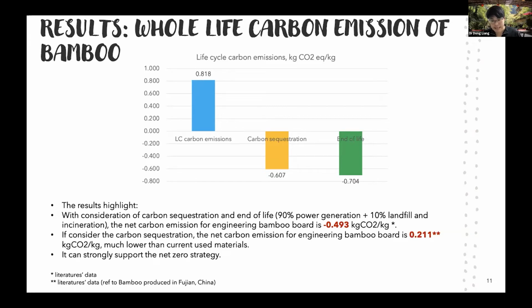For example, I applied the scenario from the European Union. 90% of the bamboo waste goes to power generation and only 10% will be landfilled. The benefit at the end of life will further reduce the carbon emission by 0.7 kilograms. That means we can reduce the carbon emission by burning the bamboo to reduce fossil fuel consumption for power generation. So if we add the benefit of carbon sequestration and the benefit of power generation from the bamboo waste, the total life cycle carbon emission for bamboo will be further reduced to about minus 0.493 kilogram CO2 emission.